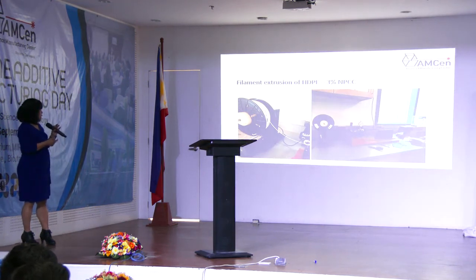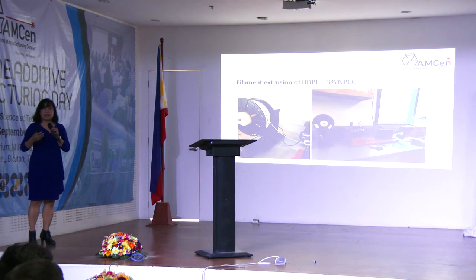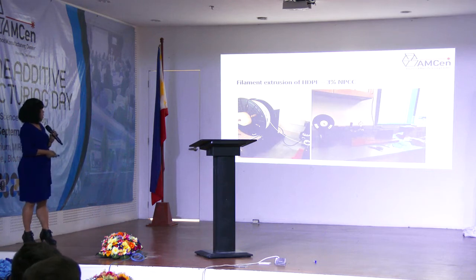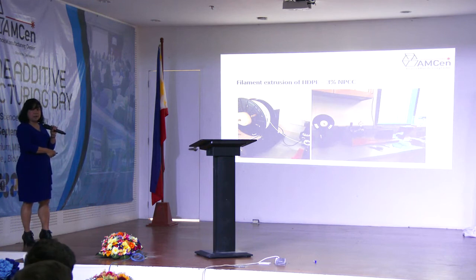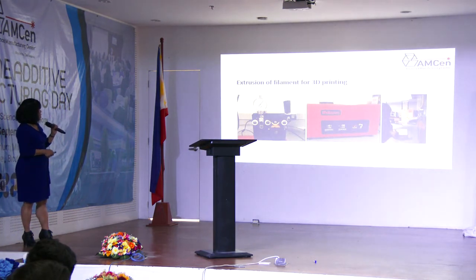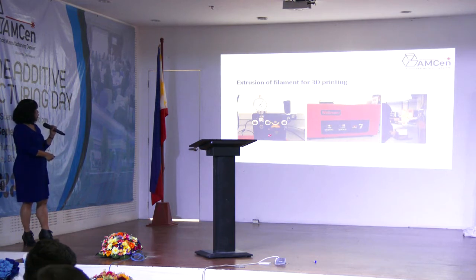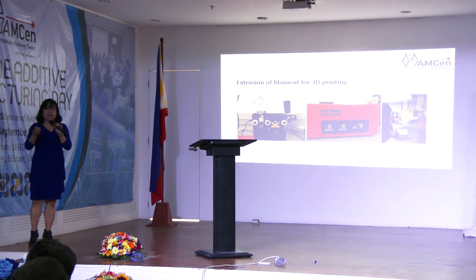And then the master batch is blended further into a virgin resin at various concentrations. In this case, we use this extruder to produce the filament. So this is the filament for 3D printing. Okay? So further, there are conditions that you need to consider in 3D printing. You need to control or optimize the extrusion parameters of the extruder, as well as control the diameter to get a consistent diameter of the filament for 3D printing.